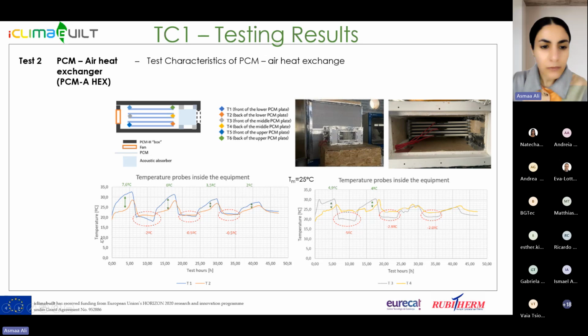From this test, first we tested the performance with different delta T's, and the PCM used has a melting point of 25 degrees Celsius. So we tested plus 10 degrees higher and minus 10 degrees differences, and we changed this difference from 10 degrees to 7.5, to 5, to 2.5 degrees Celsius, to see how the PCM can control these differences when it comes to real conditions.